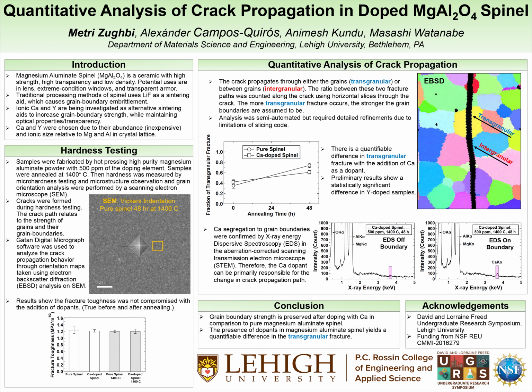But after microhardness testing, we observed microstructures of the samples and applied grain orientation analysis, performed in a scanning electron microscope, or SEM. This allows us to analyze the submicroscopic grains of the spinel. Electron backscatter diffraction, or EBSD, is an SEM technique that allows us to view orientation distribution of grains as different colors, making it far easier to distinguish between the grains of the translucent or transparent samples. The EBSD images are taken and processed through Gatan Digital Micrograph software to determine how the crack propagates.